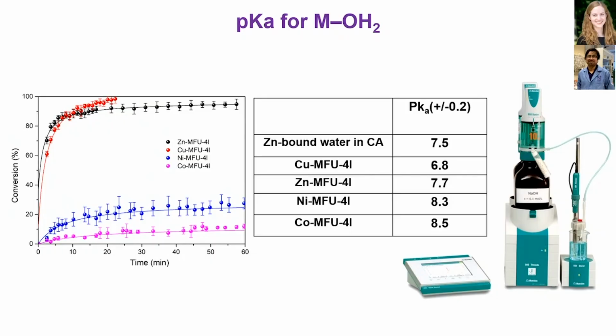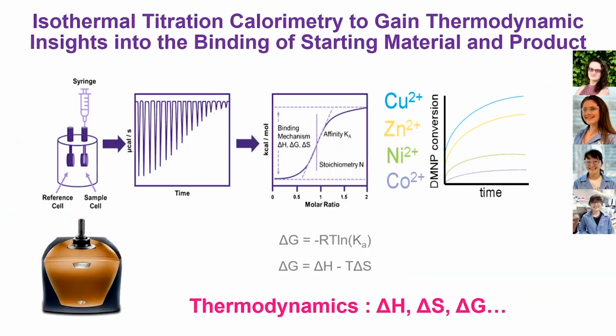That means the copper is a better acid. It works better. It makes sense. But it didn't tell us why the zinc plateaus at 90%, and why the nickel and the cobalt are off as catalysts. Now let's do a different titration. Now let's do isothermal calorimetry. So how are we going to do it? We want to try to understand the binding energy between the substrate and the catalyst and the product and the catalyst. That means we make the product intentionally and we actually titrate it.